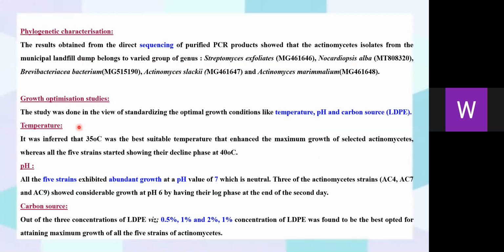Growth optimization study was done. Temperature: it was inferred that 35 degrees was the most suitable temperature to enhance maximum growth of the selected actinomycetes. pH: 7 was the optimized pH for the growth of all the actinomycete strains. Carbon source: out of 0.5, 1 and 2%, 1% concentration of LDPE was found to be the best for attaining maximum growth of all the strains.